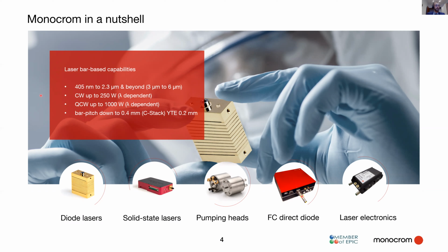Here we can offer wavelengths between 405 nanometers up to 2.3 micrometers, and we are planning to extend this region to 3 and even 6 micrometers, everything based on laser bars. For the moment, we can offer up to 250 watts CW and in QCW up to 1 kilowatt, which is wavelength dependent and refers to 1 laser bar each.